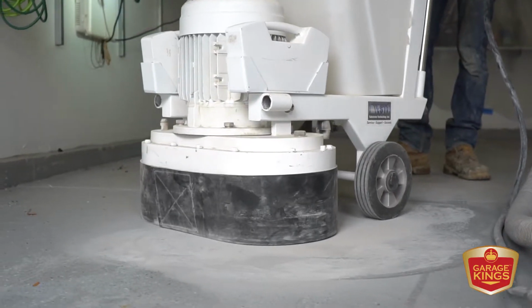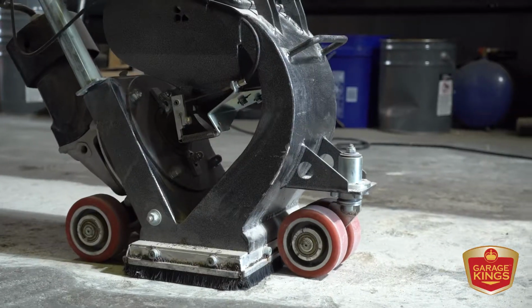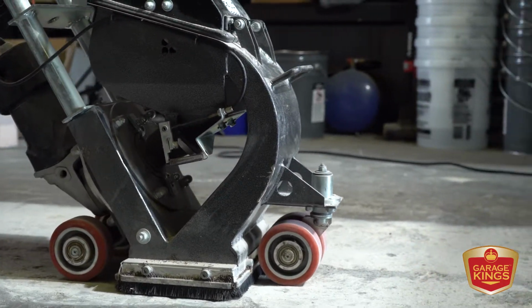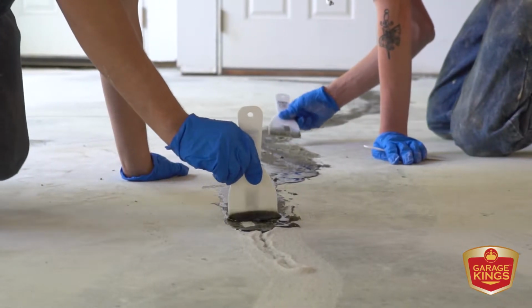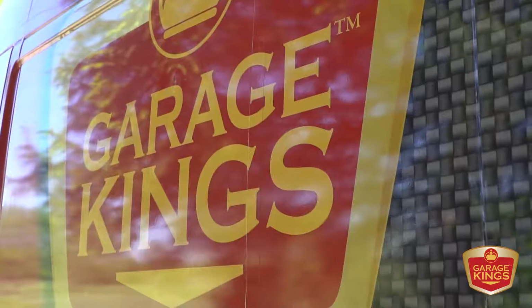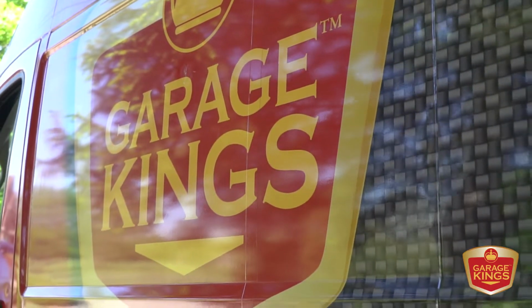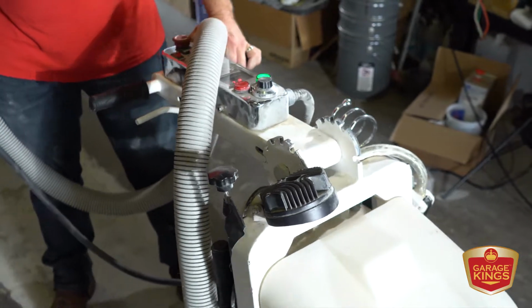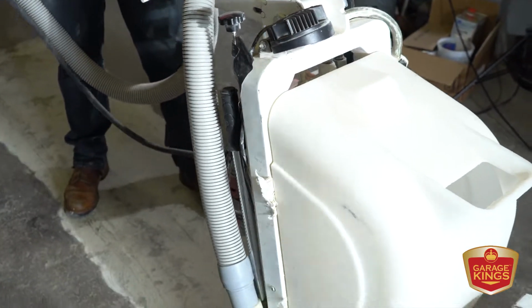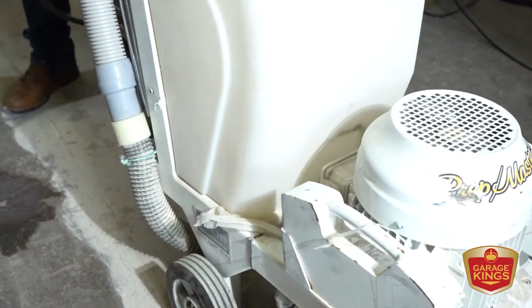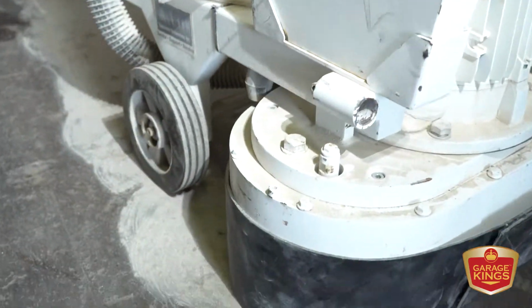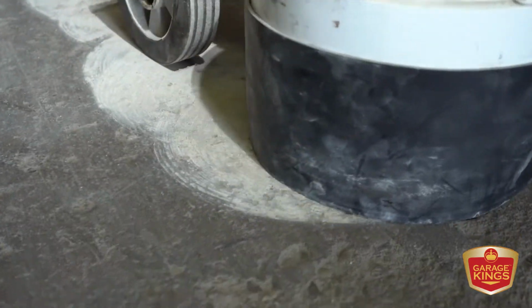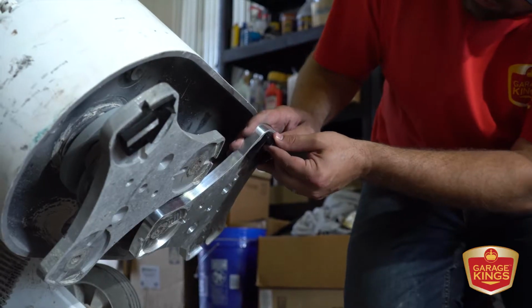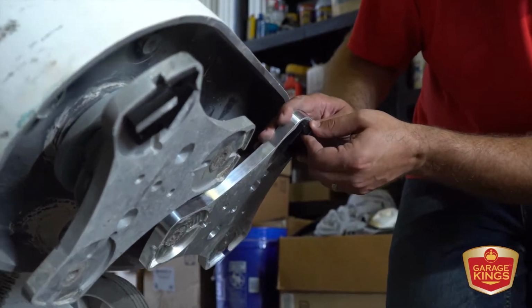Through Garage Kings Surface Prep, we utilize diamond grinding and shot blasting to create the proper concrete surface profile. The concrete surface profile allows our coating to bond to it. It's not a smooth surface. It gives it some grit, something that the coating can bond to, and that cannot be achieved through acid etching or any other method of non-mechanical surface prep. When the guys get to the job site, you'll see them set up these grinders, and they're selecting the appropriate diamond based on the hardness of your concrete and the coating we're putting down. We have different grits and different hardnesses of diamonds available.